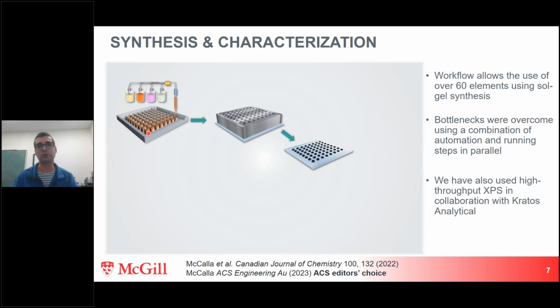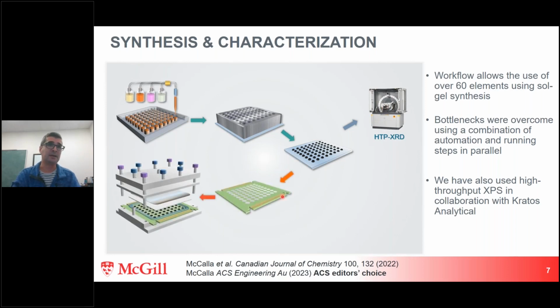So we do combinatorial research. We do it on a small scale so that we can do a lot at once. And then we take these powders, and we do X-ray diffraction. So we have high throughput X-ray diffraction that can keep up with all of these samples. And then we retrieve those same powders from the XRD. So we know the structure based on the XRD. And then we can put them into our home-assembled high throughput electrochemical cells. So we basically have 64 pads that we can put 64 electrodes onto.